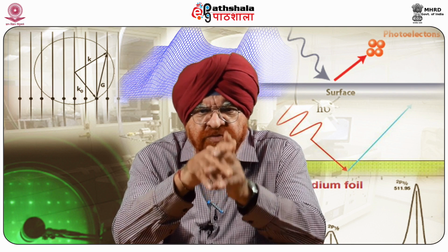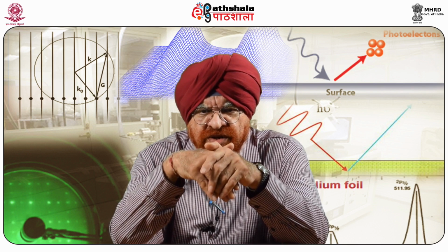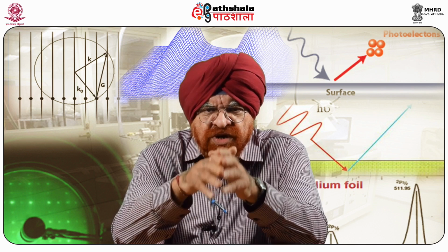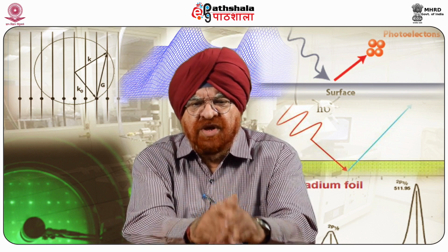On one hand, the computer effort to calculate the intensities for a certain structure has to be reduced. On the other hand, the scan of the parameter space has to be given up in favor of directed search procedures or direct methods. In fact, both strategies were followed during the last decade. The substantial reduction of computer time for the intensity calculation was made possible by the introduction of the perturbation method, tensor LEED. Of course, any reduction of computer time for the calculation of intensity of a trial structure must use certain approximations instead of applying the full dynamical theory.